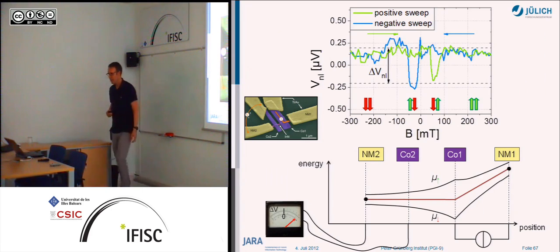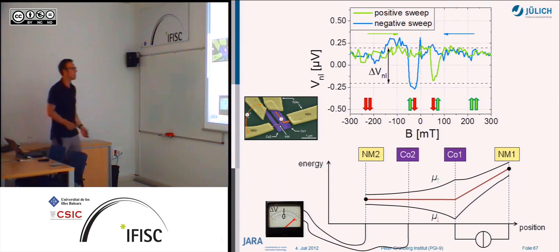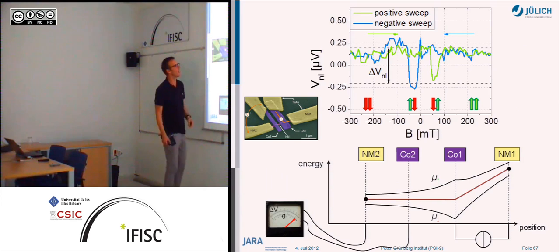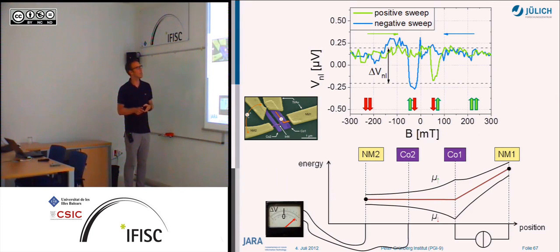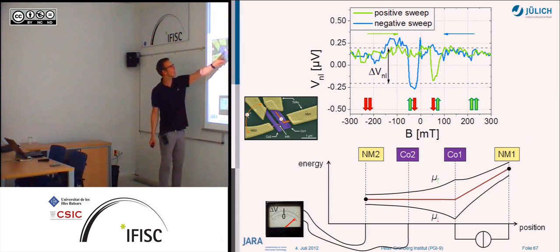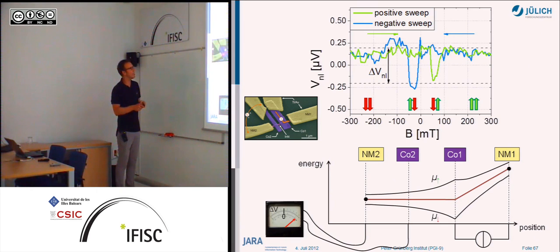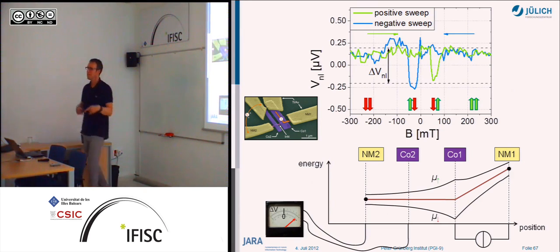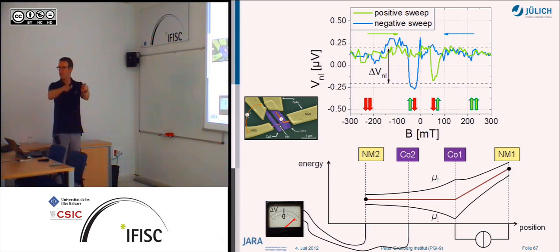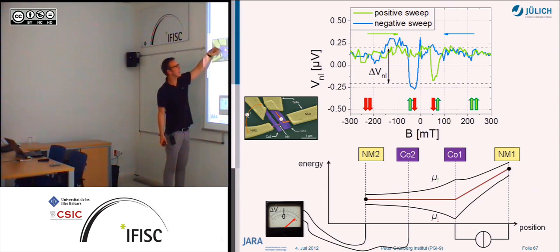And at the end, what you actually do is you drive a current here and apply a magnetic field. If you first have the magnetic field so that both electrodes are magnetized in the same direction, then you have this signal. Then if you change the magnetic field so that one electrode switches, you see a switching in the voltage you measure. This indicates that you have injected electrons from here into the nanowire, which are detected by the second contact. If you apply the magnetic field a little bit further, then both electrodes are again in the same direction but opposite to the initial case. Then you switch back to the same voltage as before, because for the transport it doesn't matter. What you measure is just whether they're parallel or anti-parallel.